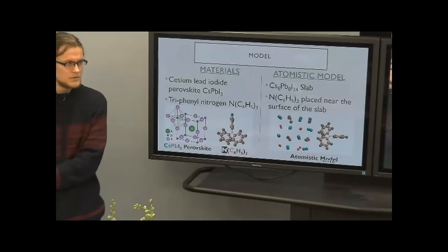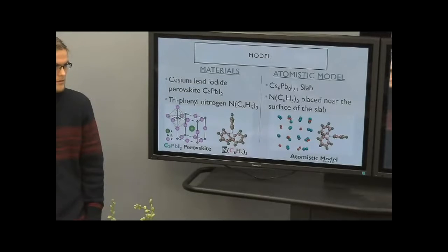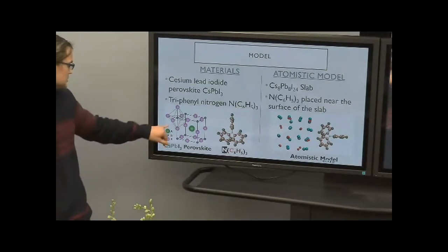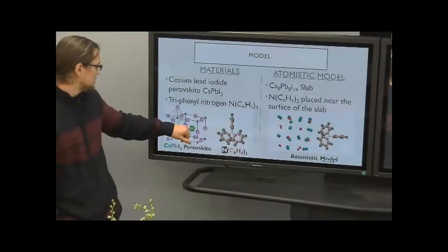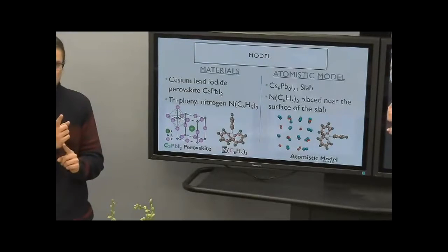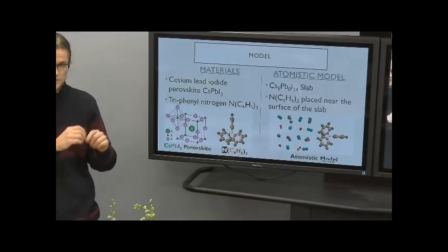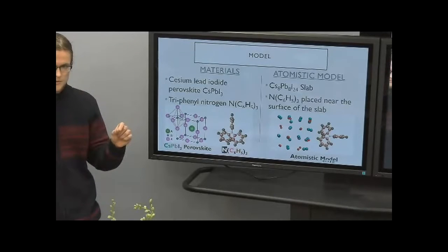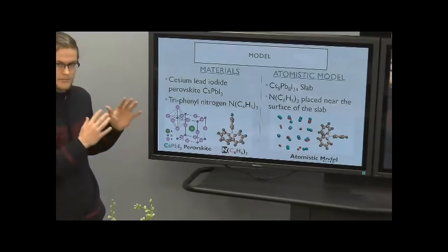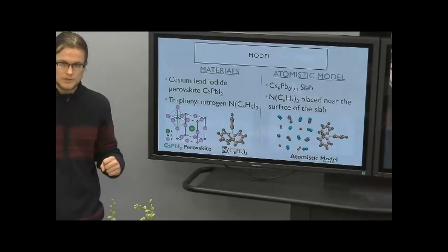In solar cells, like silicon, you need some sort of interface to produce the electric field to separate the charges. Can you make connections to this? So in this case, even though the cesium is charged, it doesn't create an electric field like the methyl ammonium would, because it can rotate and create little ferroelectric highways for the charges to separate. So in this one, there's no net internal electric field to separate the charges. So we need another molecule to pull one of the charges away.